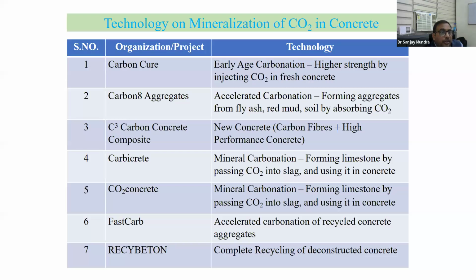Then the technology of mineralization of CO2 in concrete. These are the good organizations who are doing this mineralization part. CarbonCure is doing early carbonation and higher strength by injecting CO2 in fresh concrete. Carbon8 Aggregates: accelerated carbonation, forming aggregates from fly ash, red mud, soil by absorbing CO2. This is the carbon concrete composite C3, new concrete, carbon fibers plus high-performance concrete. Carbicrete is doing mineral carbonation by forming limestone by passing CO2 into slag and using it in concrete. CO2 concrete: mineral carbonation, forming limestone by passing CO2 into slag and using it in concrete.